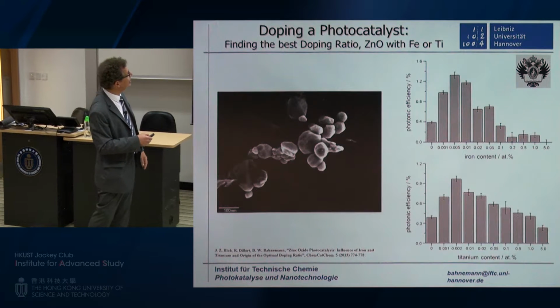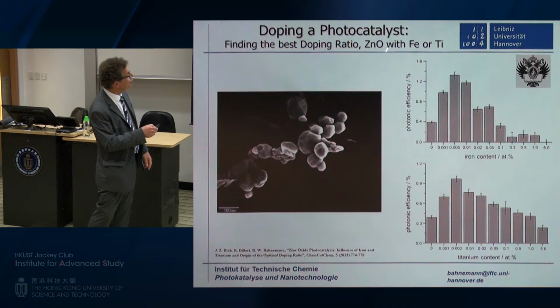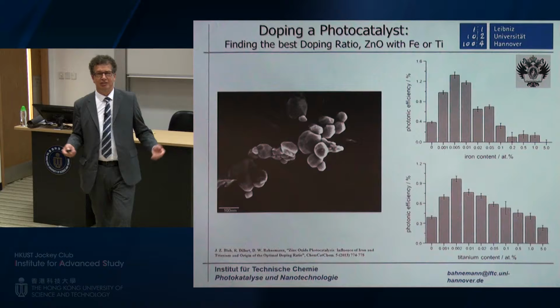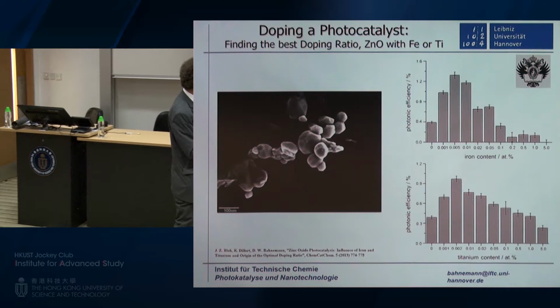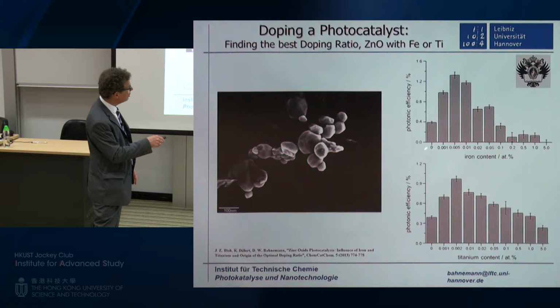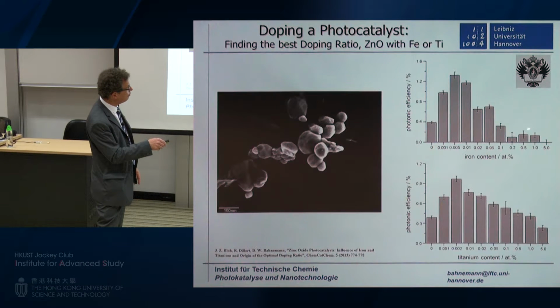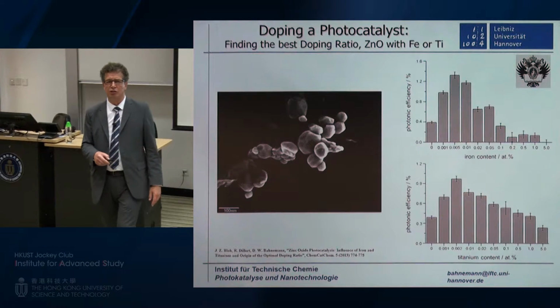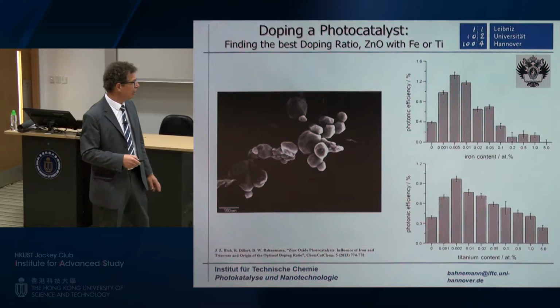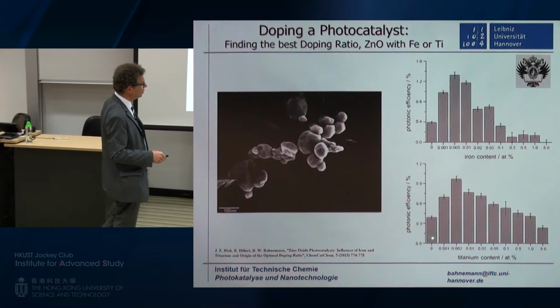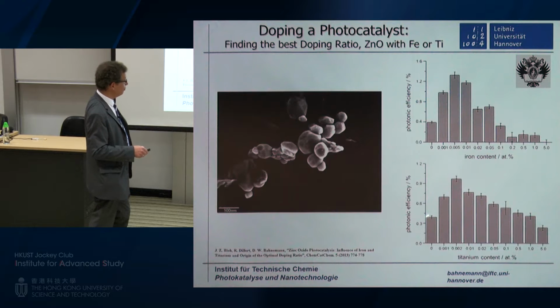He had looked at a system where he wanted to dope zinc oxide with iron or titanium, and his results were a failure, because what he had done is compare pure zinc oxide with zinc oxide containing 0.5 atom percent of either iron or titanium. As you can see, this is the efficiency, not for alcohol oxidation, but for acetaldehyde oxidation to carbon dioxide. And what you can see is the efficiency didn't increase.